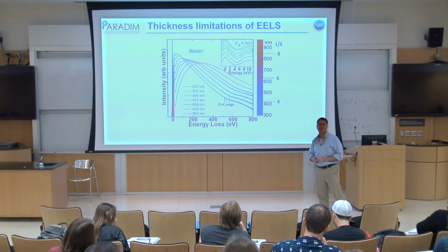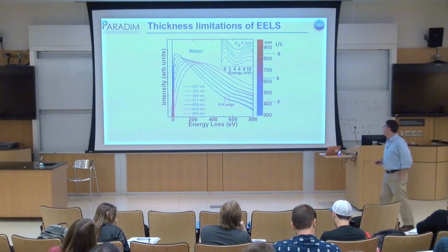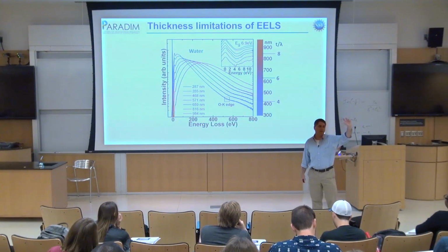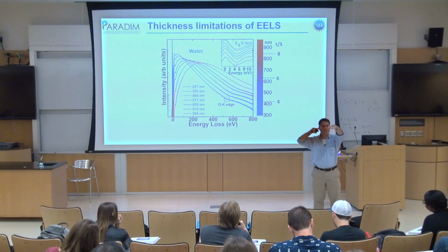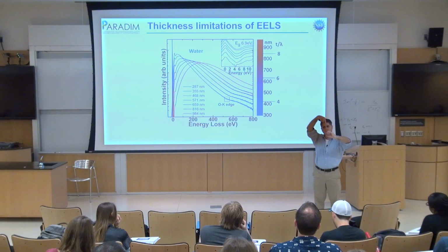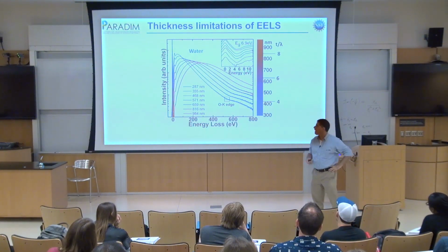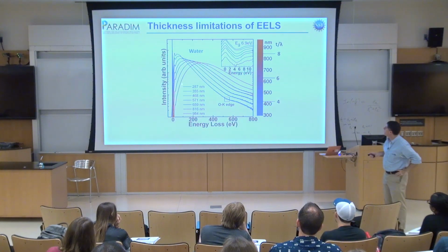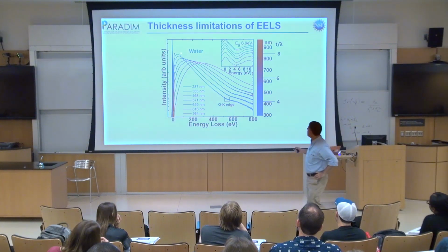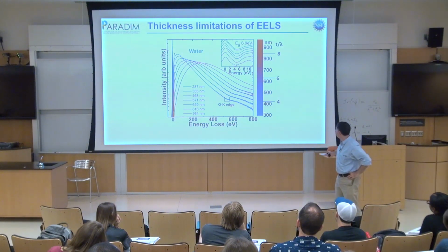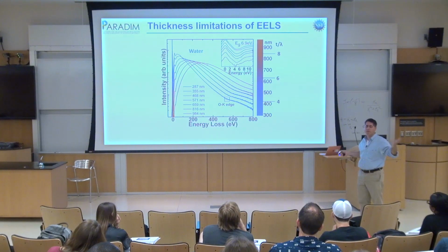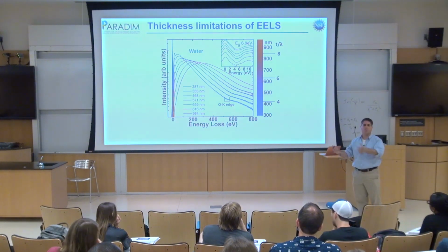You remember exactly? Yeah. So what we have over here is we've made a liquid cell. So we've had 2 silicon nitride windows. We've put water in between the windows. And then we've done EELS by firing the electron beam through this little cell, and it's 2 transparent windows. And this is the EELS spectrum that Megan took of water for a whole bunch of different thicknesses. So you can kind of see over here, this is the thinnest spectrum, and that was 300 nanometers thick, and that's about 3 mean free paths, which means everything is scattered about 3 times.